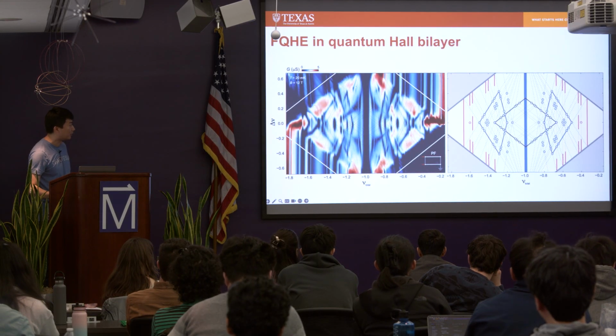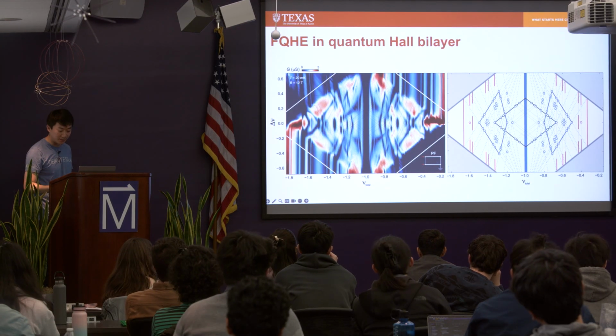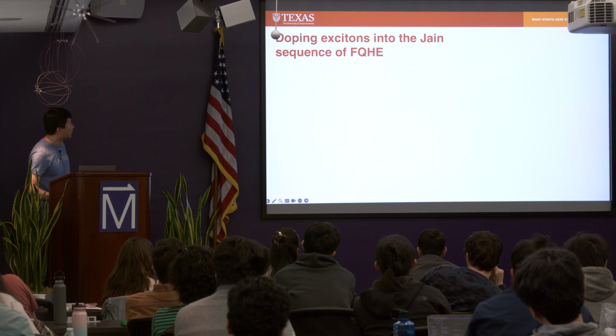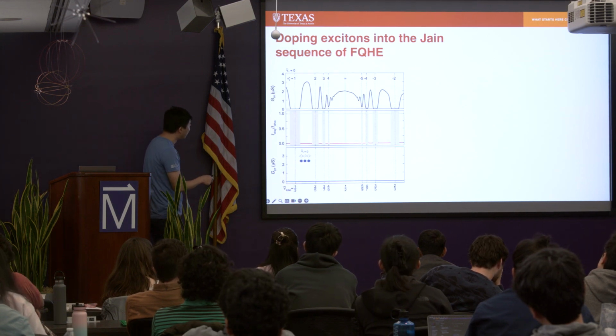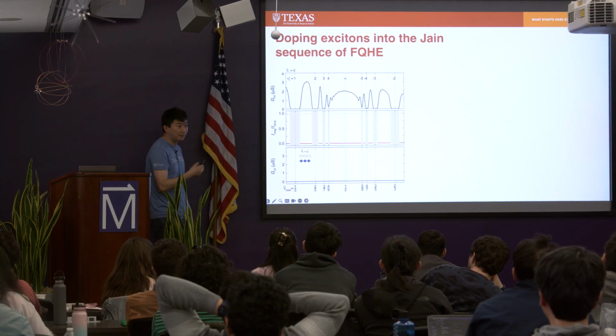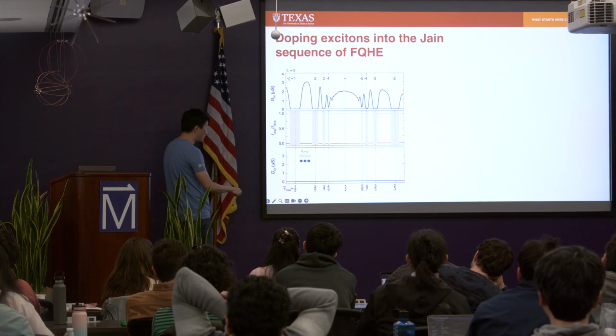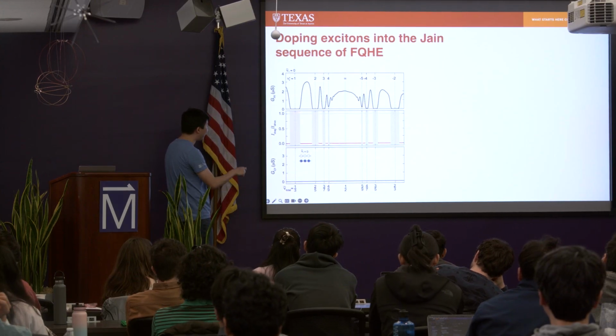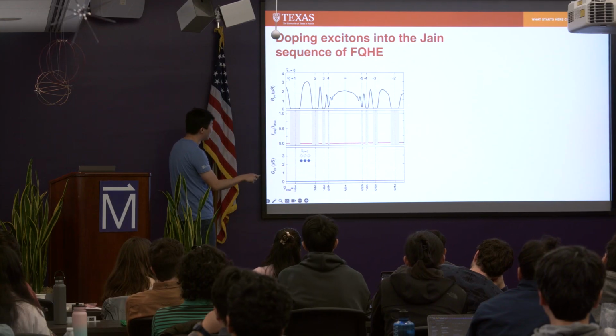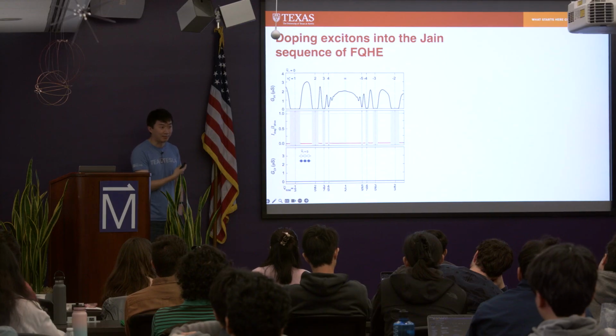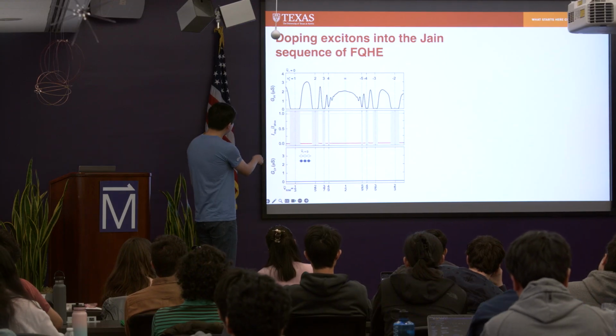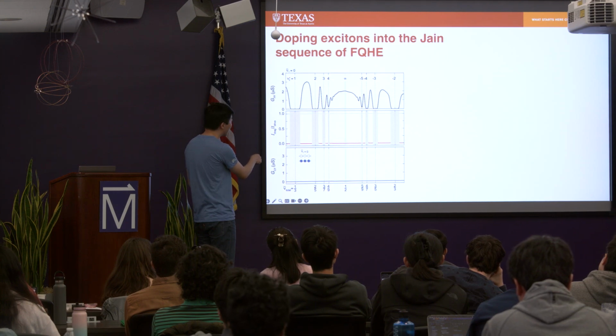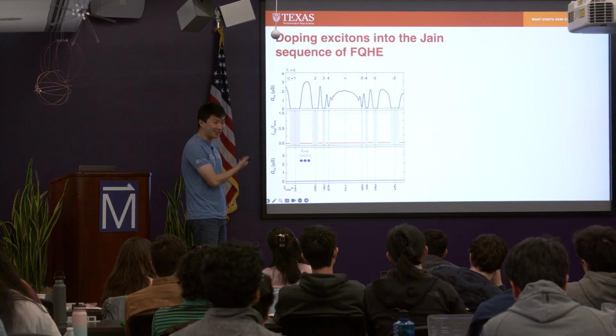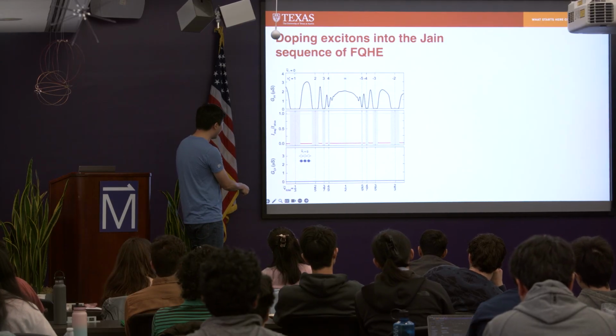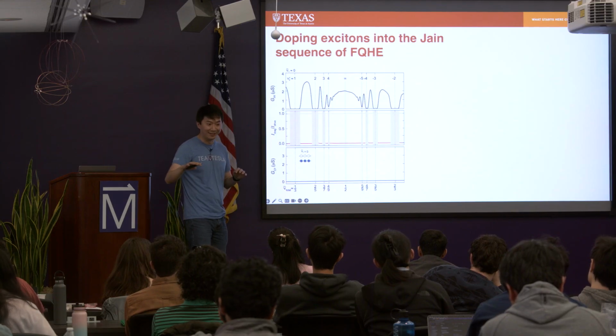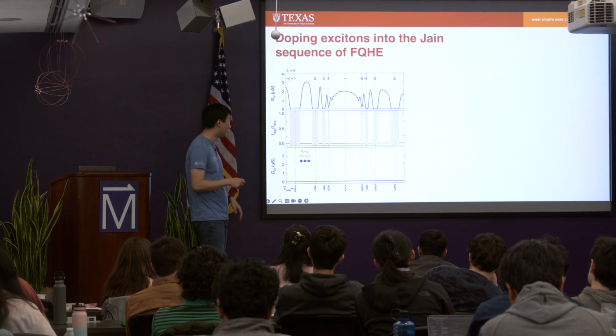but let me just show you one example of creating excitons in the presence of fractional quantum Hall effect. We call this doping exciton into the Jain sequence of fractional quantum Hall effect. The first example I give is that I put layer 1 to be 0 filling. There's no electron on the top layer, and we start to change the filling of the bottom layer. And then you see this fractional quantum Hall effect start to develop in the parallel flow channel, which looks exactly the same as the fractional quantum Hall effect in the monolayer. They correspond to effective filling 1, 2, 3, 4 of the 2 plus 0 composite fermion. And you know that this is a single layer state because it doesn't show any counterflow conductance, because one of the layers is fully insulating. When you try to flow current in the counterflow geometry, you get an insulating response, and there's no drag.